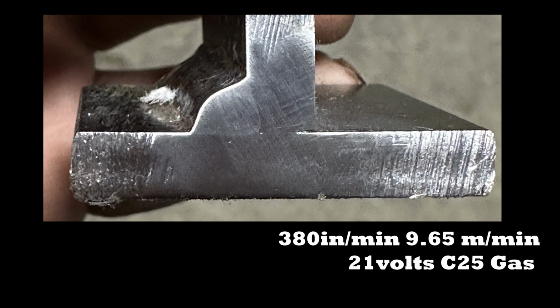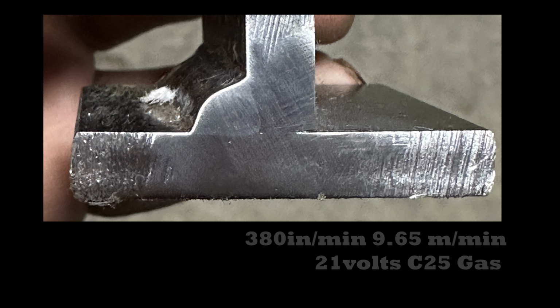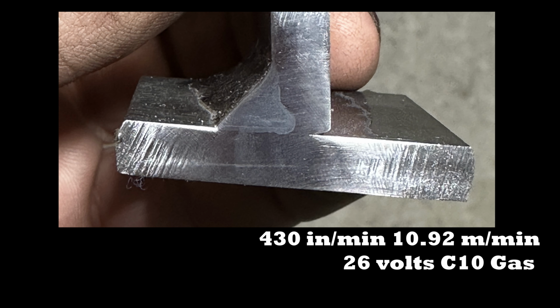Now let's look at a legit spray weld with proper settings. Huge penetration increase, which is to be expected, and that has to do with the amount of heat input as well as the high voltage and wire feed really cramming the heat into that root and getting everything fused together. And this is why spray welding on thicker plates is so effective, because the thicker you go with the short circuit process, you can get lack of fusion at that root.